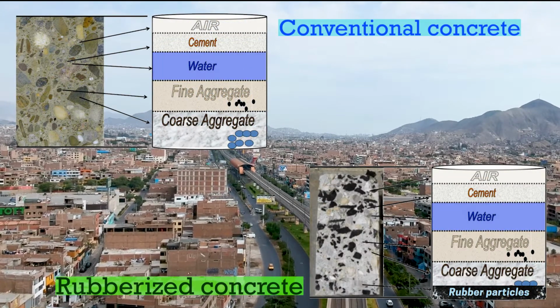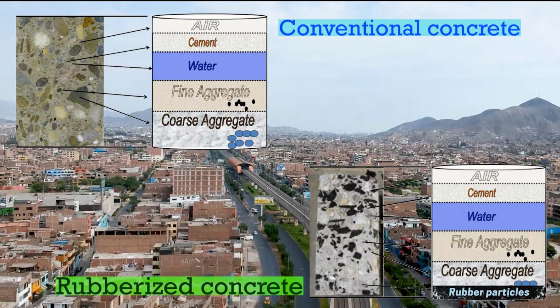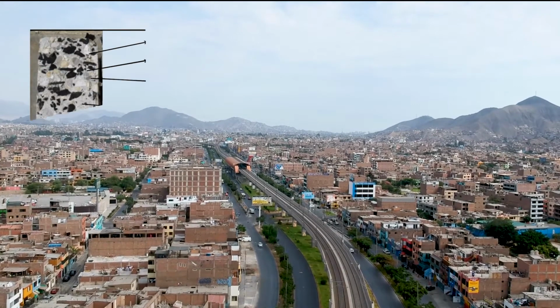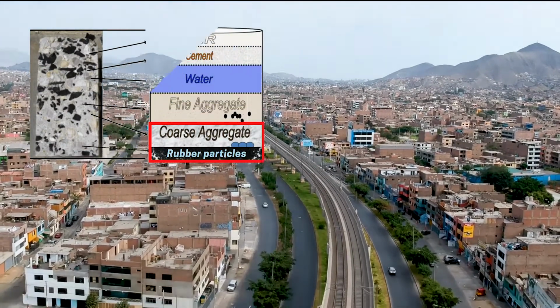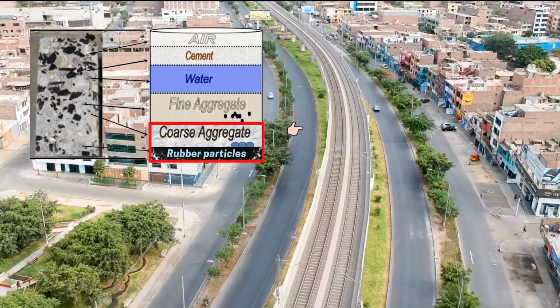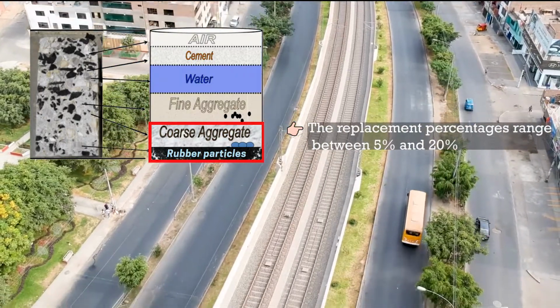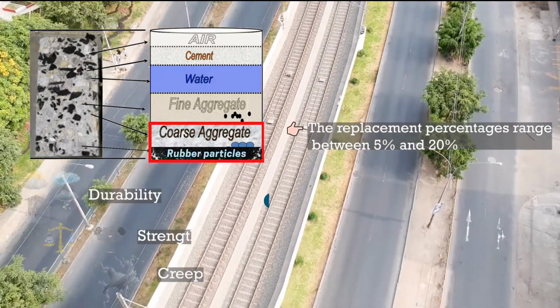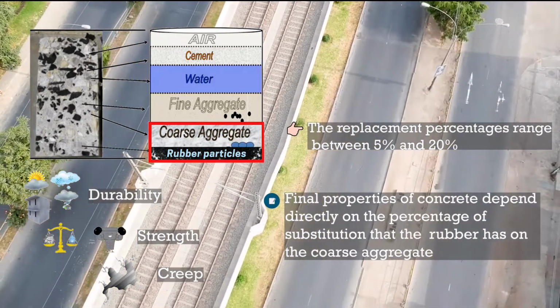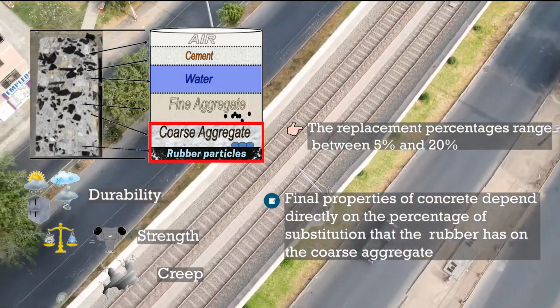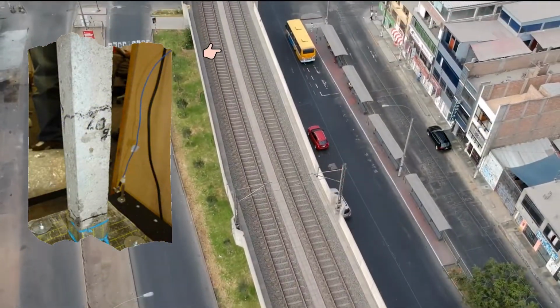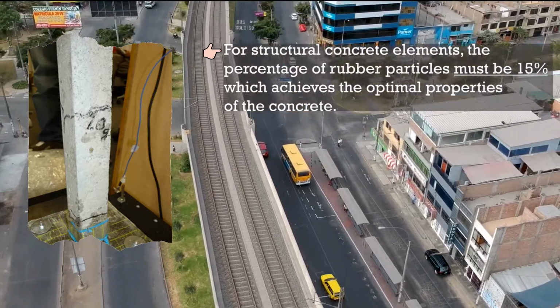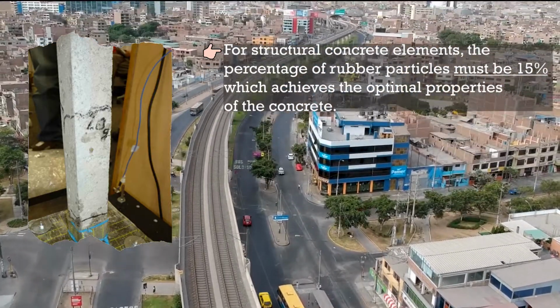The rubberized concrete components are similar to those used in conventional concrete, except for the rubber particle additions. This replaces by volume a percentage of the coarse aggregate. The replacement percentages range between 5% and 20%. The final properties of the concrete depend directly on the percentage of substitution that the rubber has on the coarse aggregate. For structural concrete, the percentage of rubber particles must be 15%, which achieves the optimal properties of the concrete.